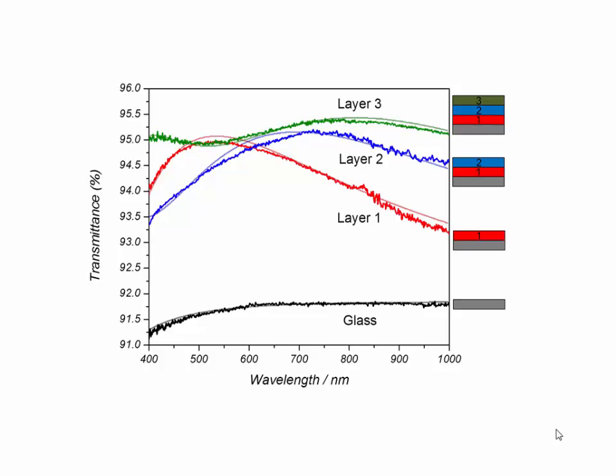We use an evolutionary algorithm to design the parameters we need for the multi-layer stack. And for a 3-layer stack on a single glass interface, we've managed to boost the transmittance from 91% to 95.5%.